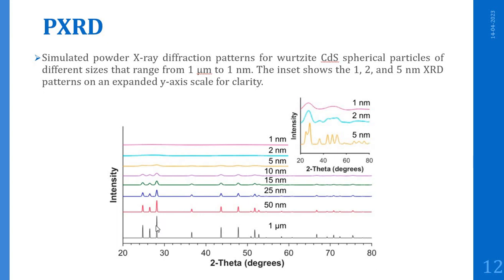Decreasing crystalline domain sizes from 50 to 25 nanometer causes more noticeable peak broadening. You can see from this figure that intensity is the height of the peak, and broadening is the width of the peak. As the particle size decreases from 1 micrometer to 50 nanometer, 25 nanometer, 10, and so on up to 1 nanometer, initially at 1 micrometer the peak sharpness was high, but as the particle size decreases, the peak sharpness lowers and the peak gets broader. So it is very difficult to analyze these small particles.